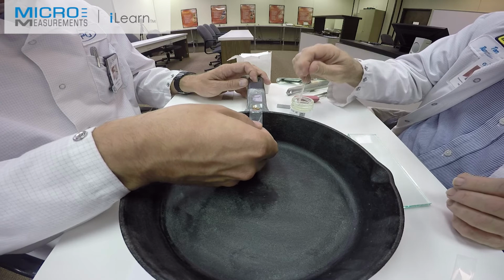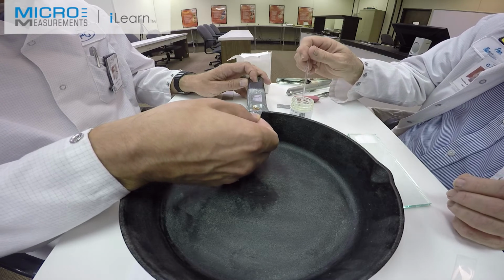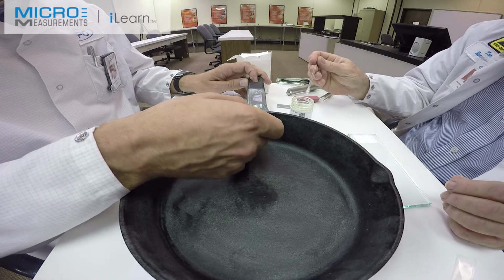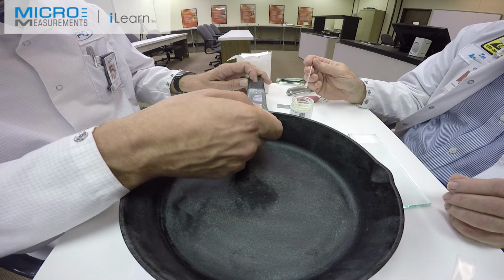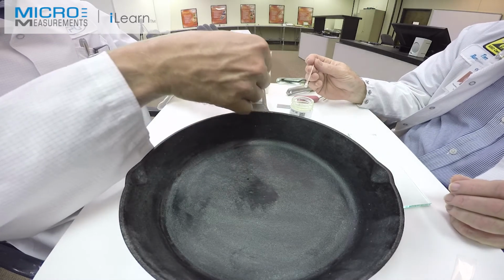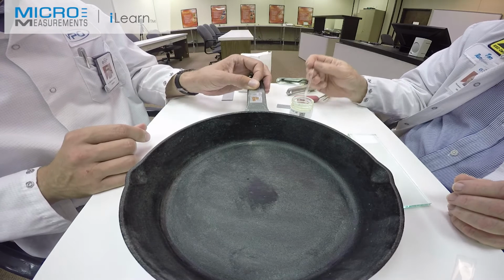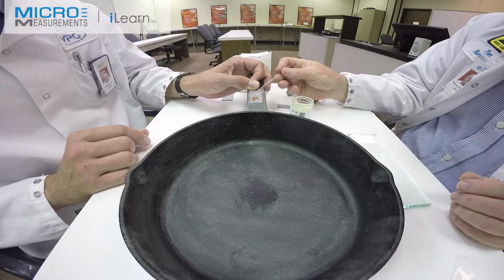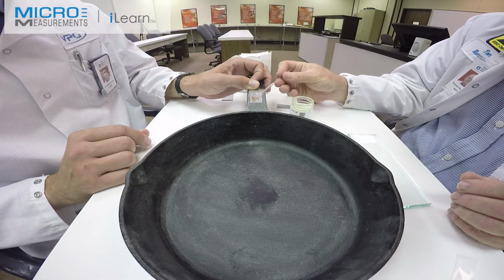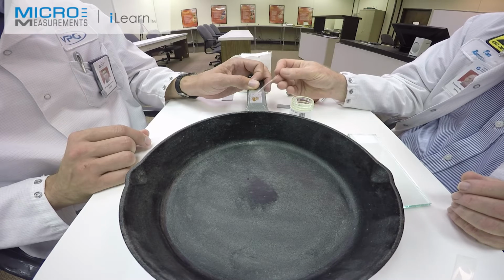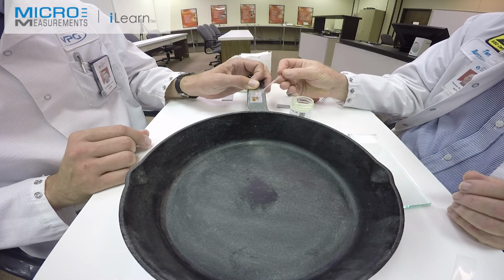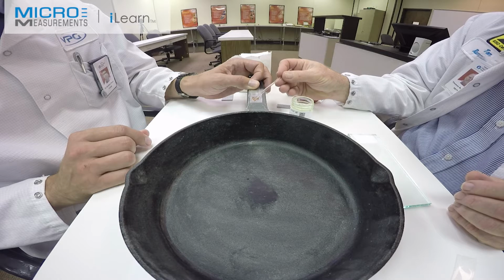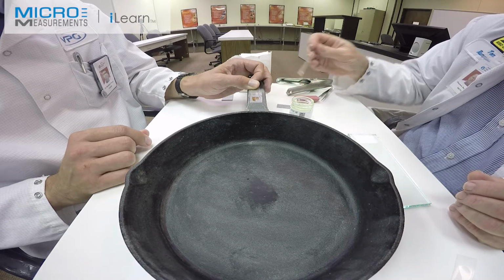You'll lift up the gauge handling tape so we expose the bonding surface of the gauge. Again, lifting at a very shallow angle, not to damage the gauge or the RTD. I'll peel it back and hold it in place for Tom to apply adhesive. Now I'm going to put a small amount of adhesive. It doesn't take a lot. You just need to wet the surface of it. Put too much and it'll just squeeze out and it'll have a mess around it.